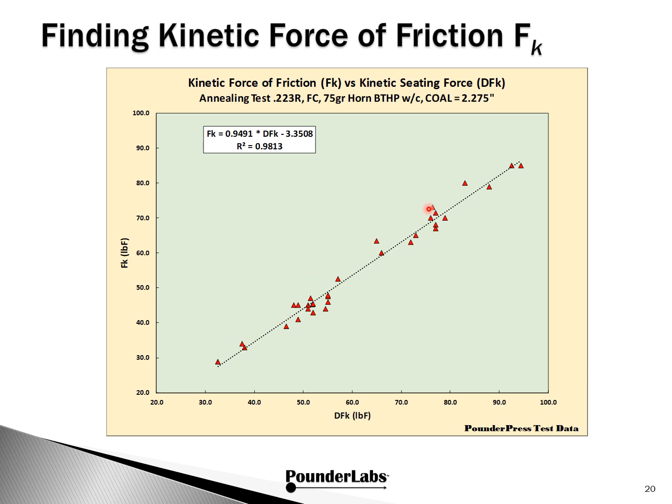These are the groups that we just completed. Down here is over annealed. This cluster here is properly annealed, and this long arrangement right here is from once fired, no annealing. So what you can see statistically, we're looking for a tight group, which will help give us more consistent shot-to-shot performance. It's also interesting to notice this dispersion here is a very broad range.